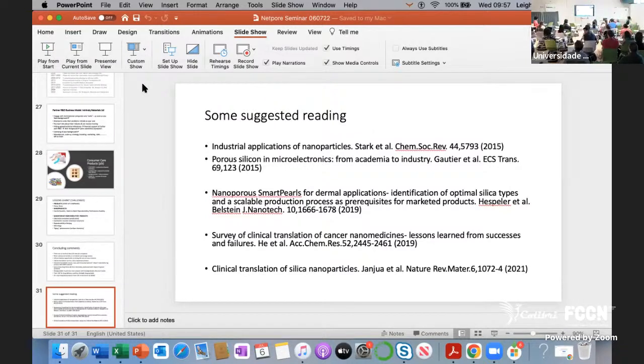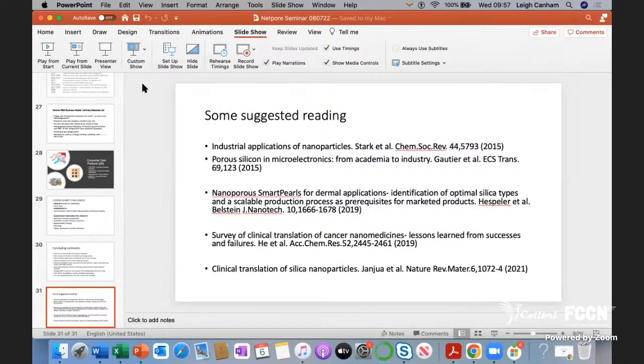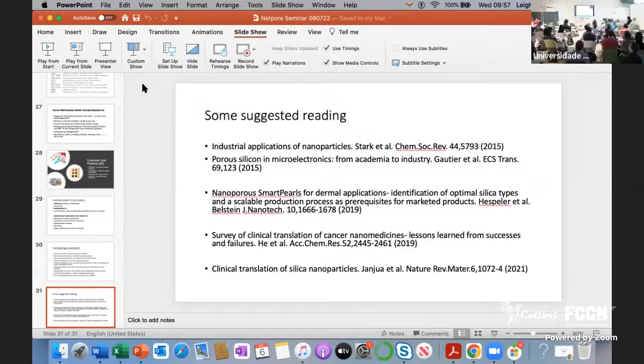So a microparticle with a nanoporous coating, the first time that was put in an animal model, it was found the particles were quite sticky to soft tissue, which again is a desired property, because then the particles basically stay where the surgeon puts them.